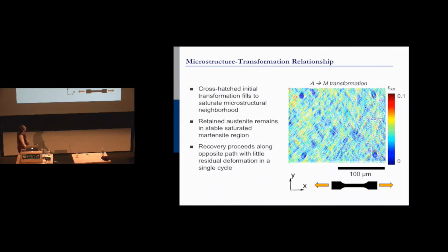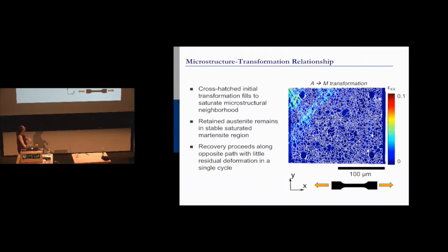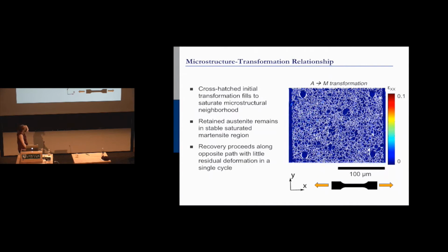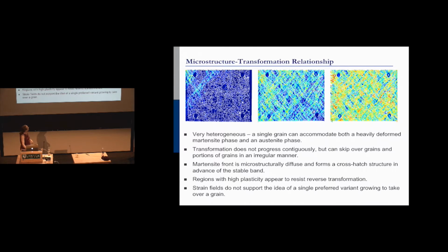And then when you release, you can see it recede with very little deformation. Okay, so that's that plateau that's coming back. That's that squishing of the stent and release. And so right away, with this new methodology, we were able to see a lot of immediate observations. One was that it was very heterogeneous. This idea of a single variant subsuming a grain, not true. You have grains that can accommodate both a very heavily deformed martensite phase and an austenite phase.